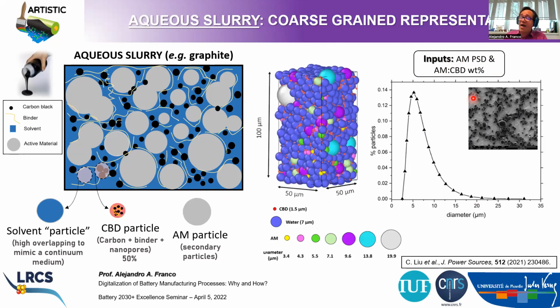And for an aqueous slurry, the approach is similar, but instead of describing the interaction between two types of particles, CBD and active material, we add a third entity, which is called the solvent particle, okay? And this is something that allows accounting very well for the viscosity and density properties of aqueous slurries. It's something that we realized by trying different approaches, right? In a similar way to the non-aqueous slurry, the input of this model is the active material particle size distribution and the weight percentage ratio between active material and CBD.